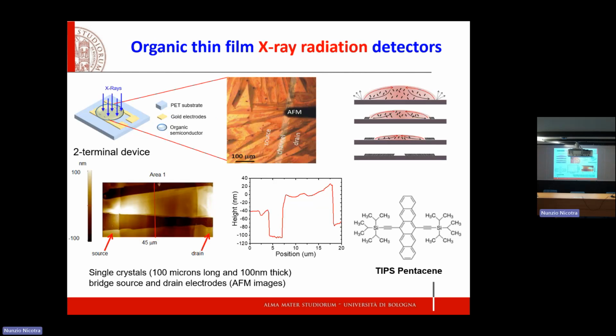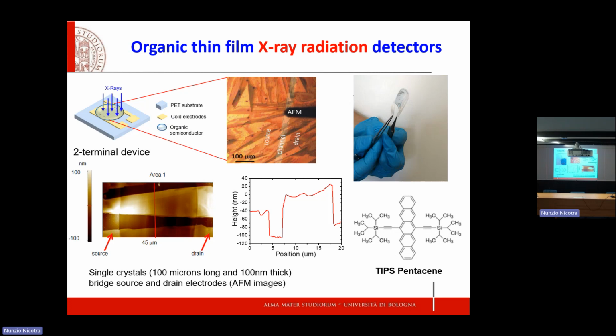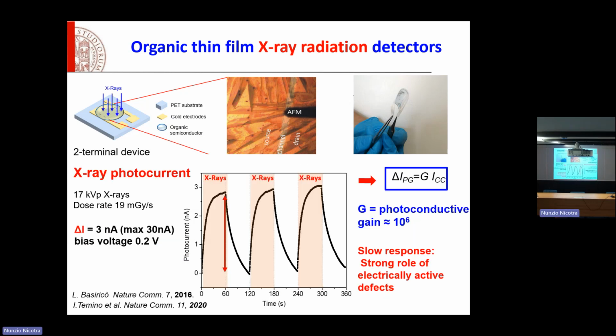Now, let's go to the point of how these materials detect ionizing radiation. Here you see a very simple two-terminal device that is based on interdigitated gold electrodes deposited onto a PET plastic thin film. On top of it, we deposit by solution with an inkjet printer this molecule, which is called TIPS pentacene, one of the most popular organic molecules, like the silicon of organic semiconductors. This molecule structures itself spontaneously by drying, as you see in the right-hand side image, into long, thin crystalline needles. These crystalline needles can be micrometers long, and they are about 100 nanometers thick, so really thin, and they definitely remain flexible, okay? Now, what happens if you put them under an X-ray beam?